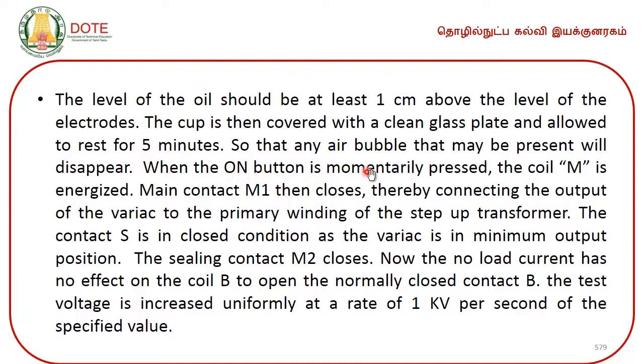When the on button is momentarily pressed, the coil M is energized. Main contact M1 then closes, thereby connecting the output of the variac to the primary winding of the step up transformer. Then the contact S is in closed condition as the variac is in minimum output position. The sealing contact M2 then closes. Now, the no load current has no effect on the coil B to open the normally closed contact B. The test voltage is now increased uniformly at a rate of 1 kilovolt per second of the specified value.